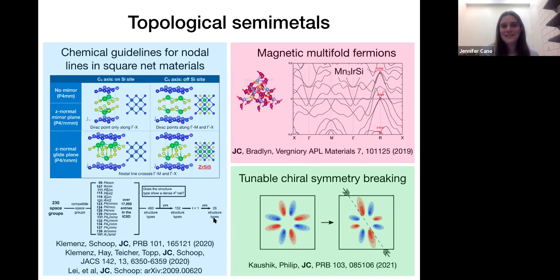You're bringing up a different aspect, which is charge density waves. In some examples, a charge density wave is due to interacting physics, but it can basically give you a lower space group. It breaks some crystal symmetry and gives you a lower space group. And then we might be able to still get out a band structure with the charge density wave. So I think there is some algorithmic thing that we could do, which is start with a classification in one space group, consider a charge density wave that breaks some symmetry, and then move down to a lower space group and ask, is that lower space group realizing a topological phase? There's some algorithmic way to use this data and predict which semimetals would yield topological insulators with a charge density wave.